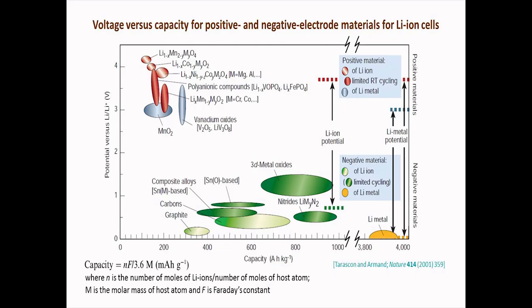So the voltage is not sufficient for high energy density; one also needs capacity, which is basically the amount of lithium that can be stored, or equivalently the amount of electrons that can be stored per unit mass of the material. This entire map shows a variety of materials with different capacity and different voltage with respect to some reference. In this case, it is lithium plating on lithium which is used as the reference, which is taken as 0 volt.